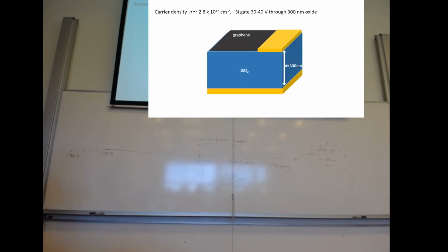And there's one thing we have to emphasize, for theoreticians specifically. When we say a gate voltage, I've read papers from theoreticians who put this potential into Hamiltonians, which mistakenly makes this energy very weird and gives strange results. Actually, when you put a gate voltage, it does nothing but induce some carriers at the surface between graphene and the silicon oxide. It's purely classical capacitive coupling.